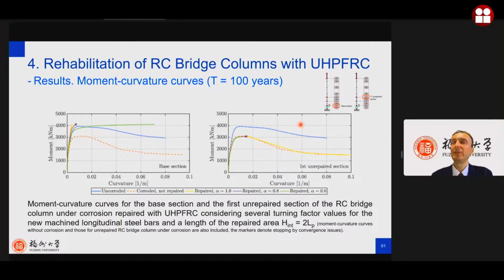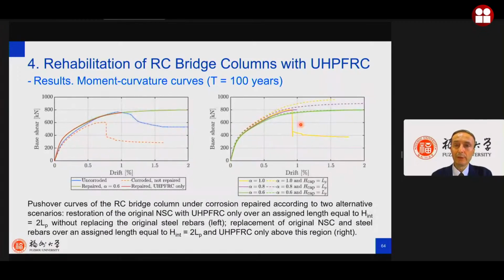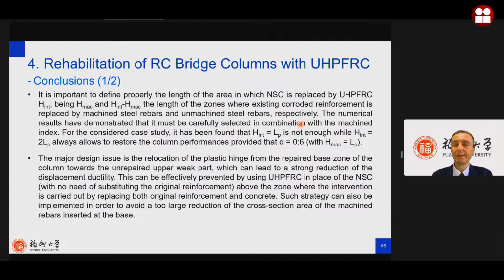And the other message is this: it's very good to use this confinement with ultra high performance concrete, but you should pay a lot of attention if the most sensitive section becomes the first one above the repair area. And so from our point of view, the best compromise was to use an intervention with ultra high performance concrete that has a dimension of twice the plastic hinge dimension, and to change also the steel reinforcement using a tuning factor of 0.6.